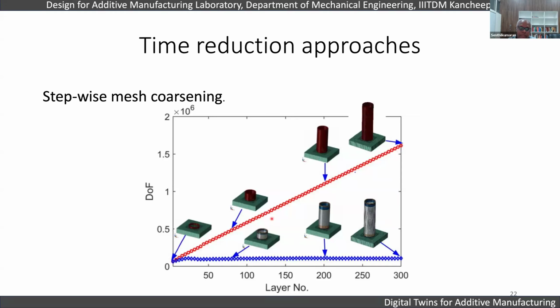You can see that initially this is the one approach where you have used uniform meshes for different degrees of freedom. So for 300 layers, you could see that the degrees of freedom was somewhere around 1.5 times 10 to the power 6. But here you can see if you use a stepwise coarsening mesh scheme, only this is the fine mesh and this is the rest of the coarse mesh. You can see it is reduced to a very small amount of time. So you can see that the time reduction approaches are very, very favorable.